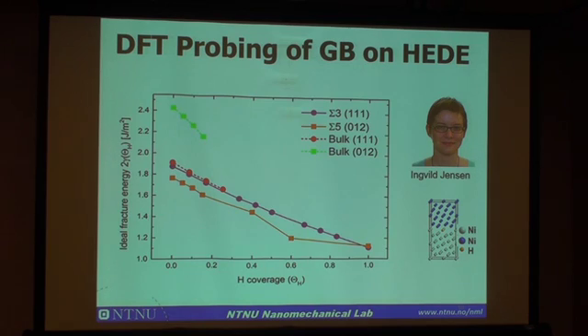Here are some typical results. Some of you may already have seen them. Here are the fracture energies, and it seems grain boundary has a strong influence on the fracture energy. Sigma 3, if we look at the circle here, sigma 3 grain boundary has a little effect, but sigma 5 has a dramatic effect. This shows that DFT is a very powerful tool to probe the effect of grain boundary.